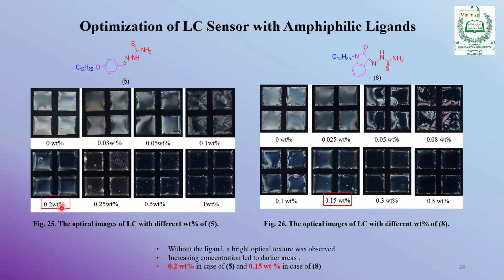So from here we see this is the optimized concentration for this amphiphilic ligand. And in the case of the second amphiphilic ligand containing the certain moiety, we see that 0.15% of ligand, we are at the dark image. Okay, the dark texture is being obtained. So these are the optimum amphiphilic ligand concentrations which we need for the liquid crystal sensor to work or to sense. So without the ligand, a bright optical texture was observed, increasing the concentration led to darker area, 0.2% of first and 0.15% in the second case is the optimized concentration. Okay.